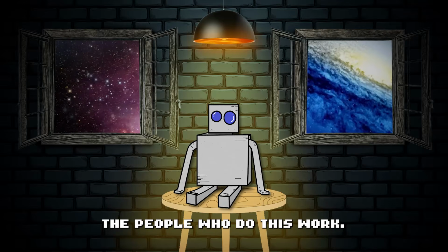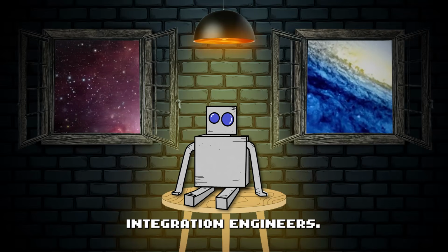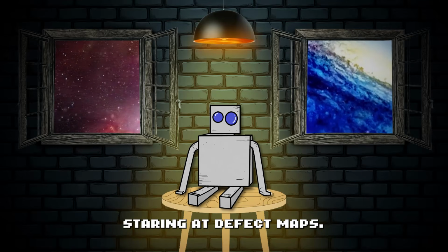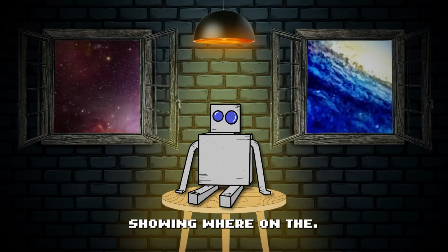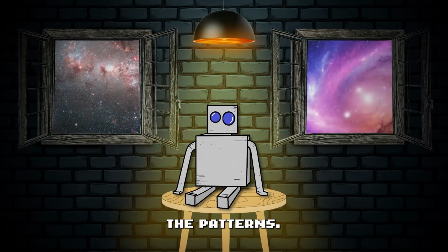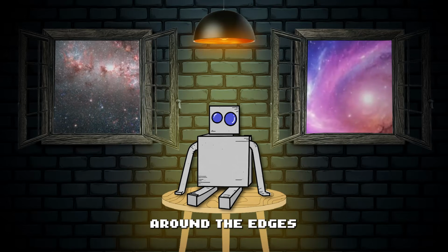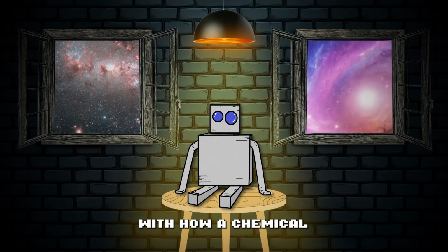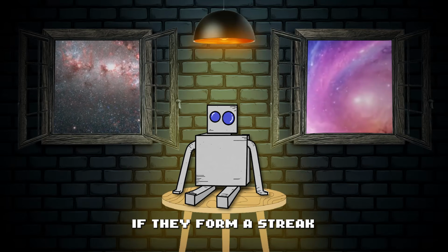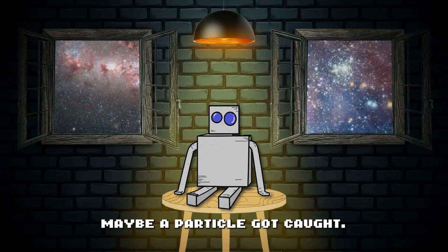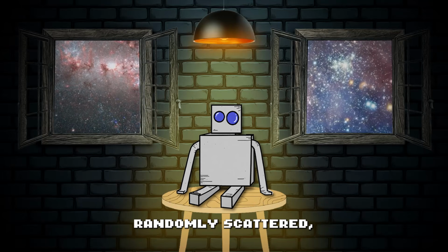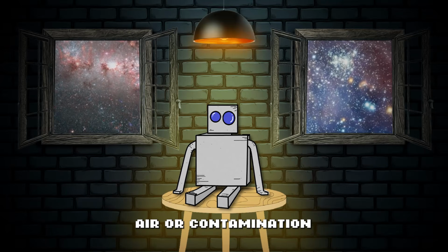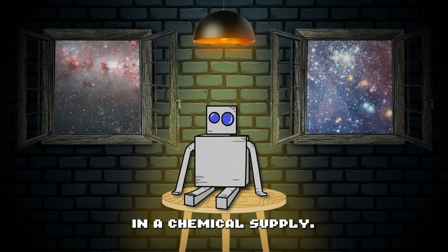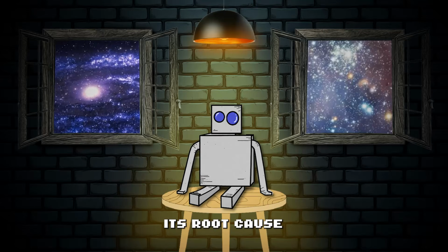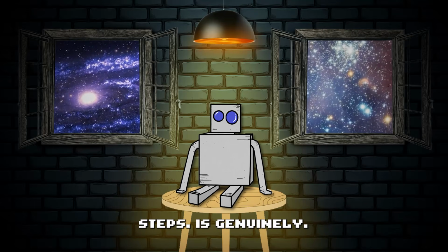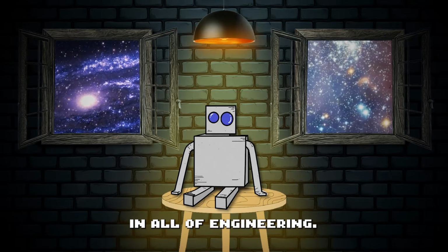The people who do this work, yield engineers, process integration engineers, they're detectives. They spend their days staring at defect maps, which are plots showing where on the wafer the bad dies are. The patterns tell stories. If the defects cluster around the edges of the wafer, that might point to a problem with how a chemical is flowing in a deposition chamber. If they form a streak across the wafer, maybe a particle got caught on a transport arm. If they're randomly scattered, you might be dealing with particles in the cleanroom air or contamination in a chemical supply. Every defect is a clue, and tracking it back to its root cause through hundreds of process steps is genuinely one of the hardest diagnostic challenges in all of engineering.